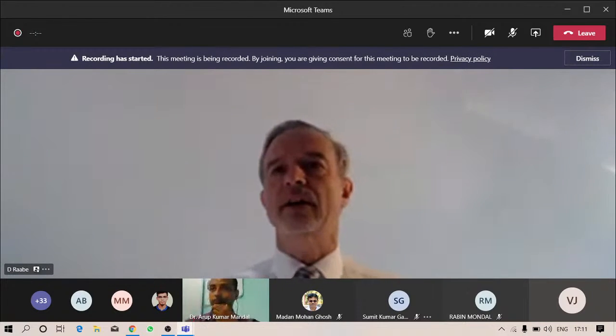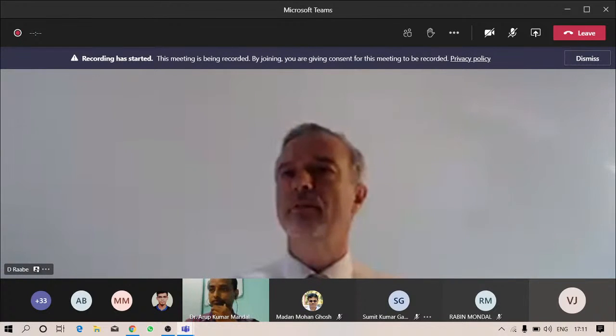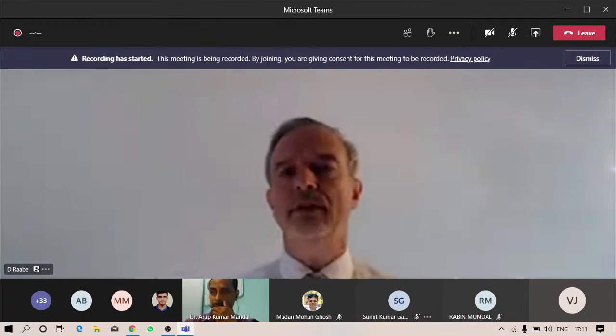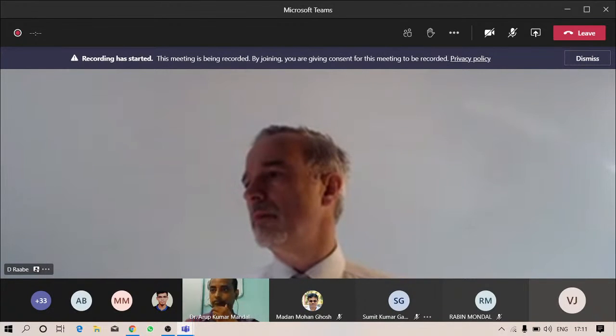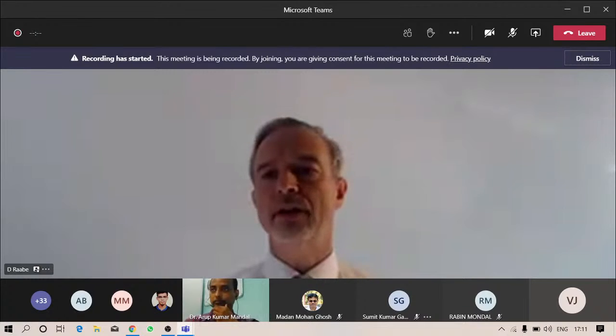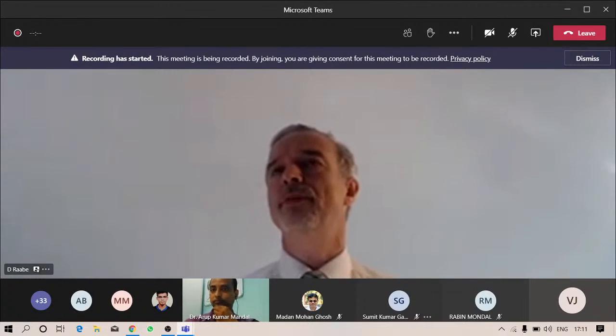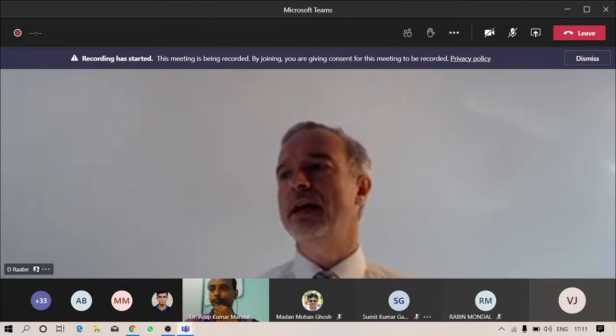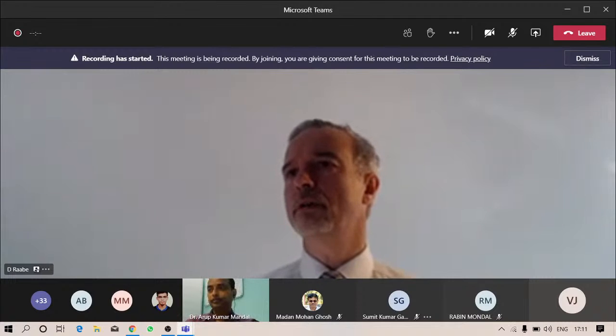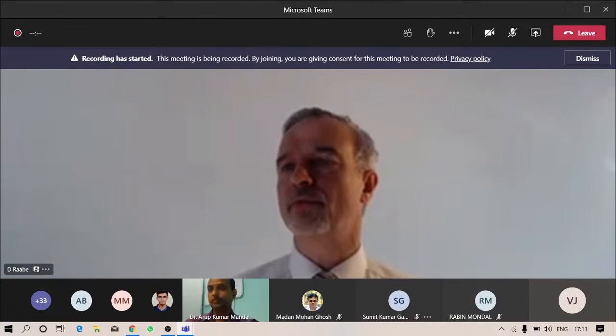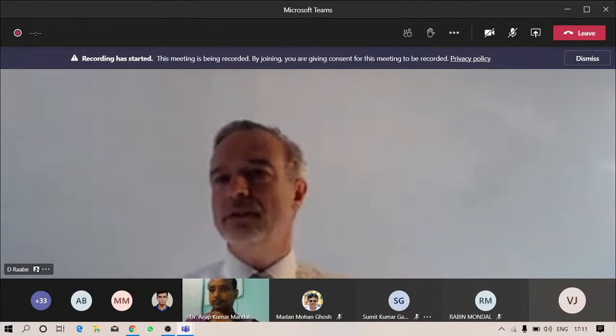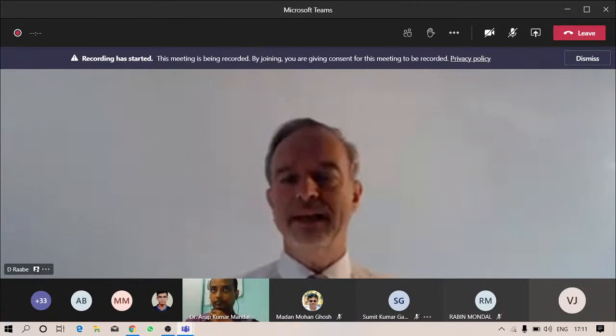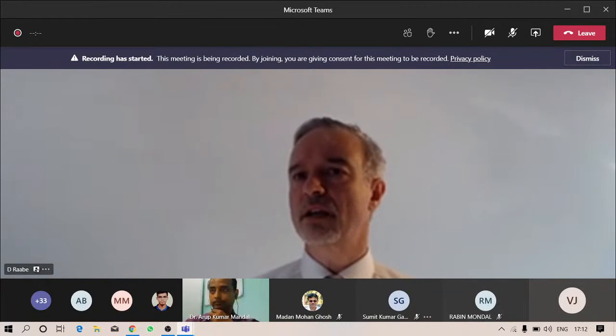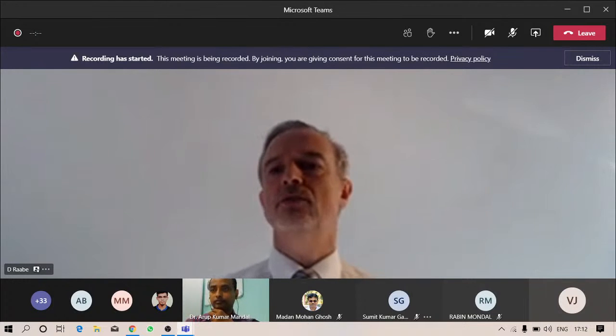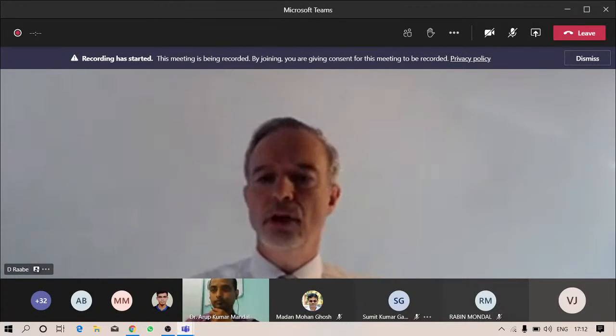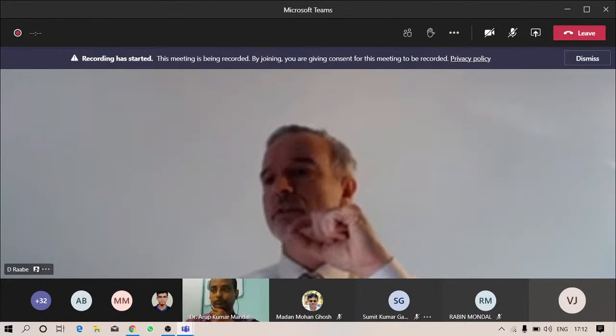Yeah, that is a good question, and I only had time to mention this very briefly at the end. So how we do it in DAMASK, how we currently develop this, is in principle like what you know from the classical Griffith criterion from your textbook. When you remember in classical Griffith crack mechanics, you balance the elastically stored volume energy when you load a body against the free surface energy that you have to provide when a crack opens. And when you add to this the local anisotropic plastic energy, then you can put these three contributions, the elastic energy, the plastic energy, and the surface energy, into a Landau functional, where you essentially subject it then at an integration point to competition with elastic, plastic, or phase transformation dynamics.